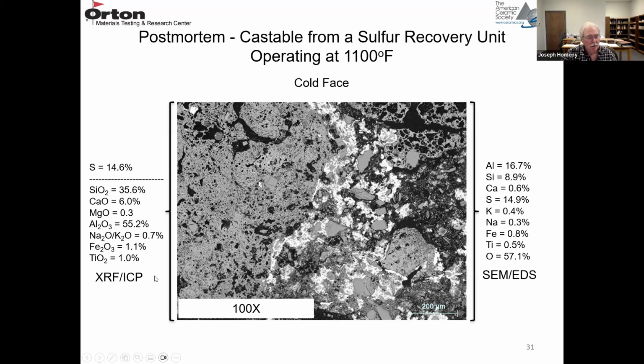So this is the cold face. And we did a bulk chemistry by XRF ICP on the cold face. It's silica, lime, and alumina. So it's a calcium aluminate bonded castable. And even on the cold face, it has a sulfur contamination. Sulfur has diffused through the refractory to the cold face, almost 15% sulfur. The SEM analysis here is in elemental form, alumina, silica, and calcium, and you see the sulfur. And you have a high oxygen because it's not calculated out in oxide form, but it would be Al2O3, SiO2, and CaO.